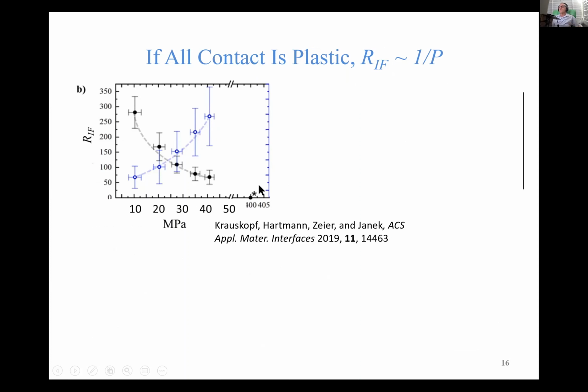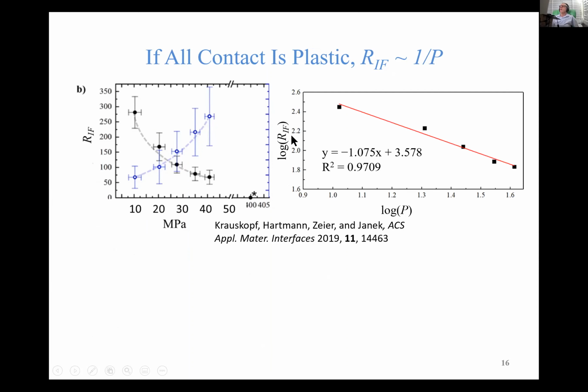So here's some data from Jürgen Janek's group, and the black dots represent the interfacial resistance that he measured as a function of stack pressure. What I did is I took the data off his graph and replotted it as the log of the interfacial resistance against the log of the pressure. That gives a pretty straight line with a slope pretty close to -1. By the way, this is the only right way to do this.